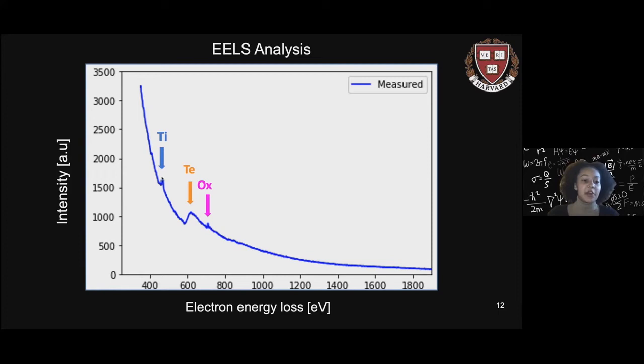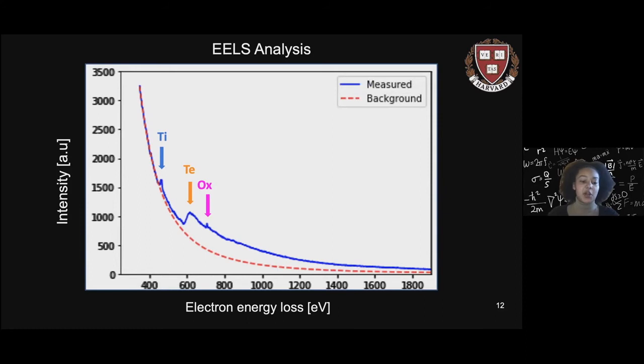And so by knowing exactly where these peaks are, we then use a simple power law curve as our background. If we're interested, for example, in the titanium, we'll fit this background curve and then take the difference between our measured signal and our background curve to produce a subtracted signal that is free of instrumental resolution, and we're able to analyze directly. By performing this analysis across our entire sample, we can determine exactly how much titanium exists at every point in the sample, and do the same for all of the other elements.